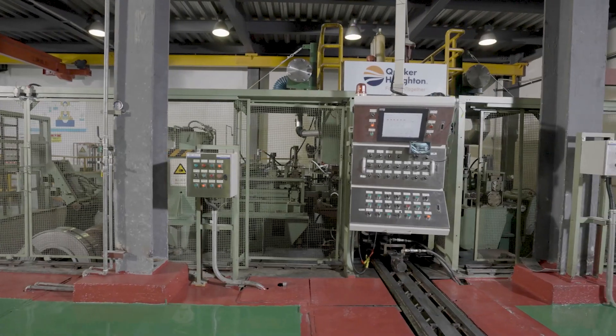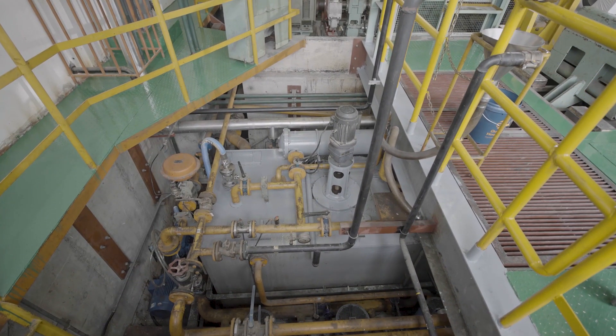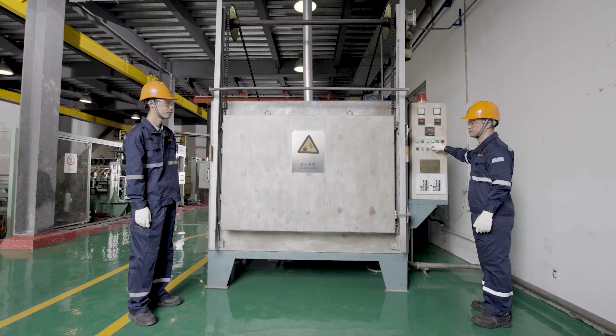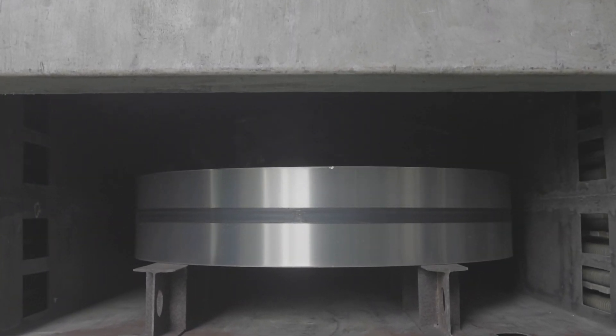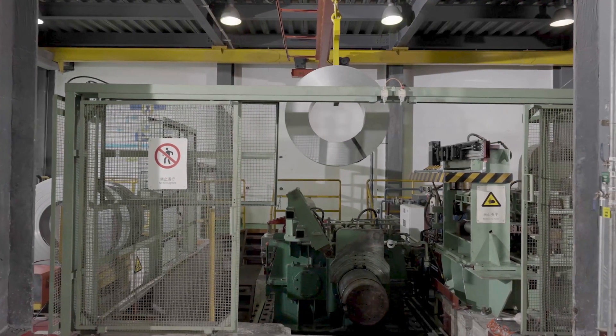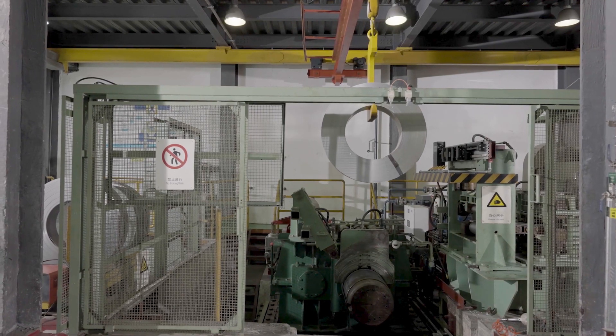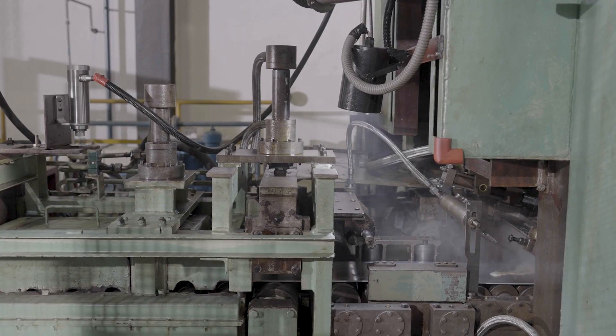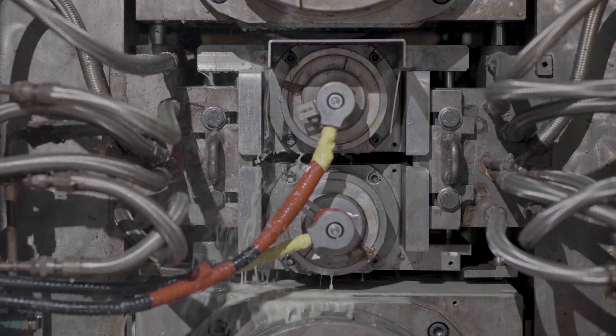Quaker Houghton's 4-High Multifunctional Reversing Mill provides the flexibility to study the properties of aluminum rolling, new product development, and new equipment validation. With high-speed flat rolling lubrication and multiple process settings, the pilot mill can be configured to perform hot rolling for aluminum coil and slab starting from 10 millimeters down to 2.5 millimeters thicknesses and at temperatures up to 600 degrees Celsius or 1,112 degrees Fahrenheit.